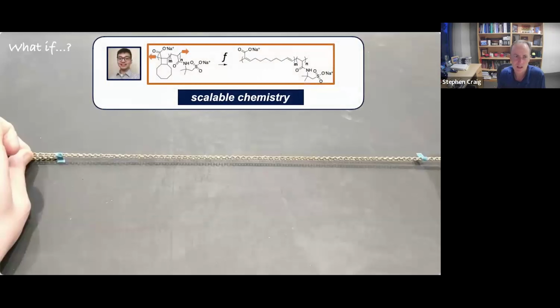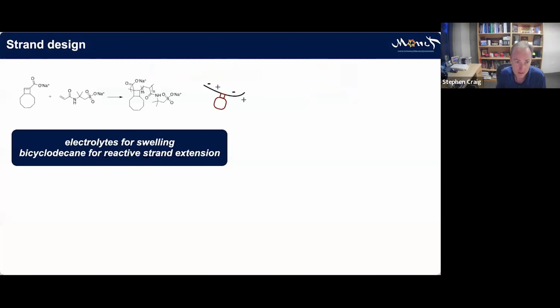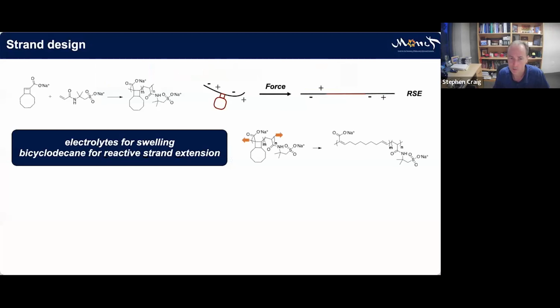Zi developed some very nice chemistry that allowed us to embed large quantities of strain-releasing stored length mechanophores into polymer chains, with the idea that I could take that chain and under force it would grow longer. So here's the specific transformation: again breaking a cyclobutane, not to break the chain, but to form a couple of alkenes held together by this fused ring, which now opens up to increase the length in the main chain.